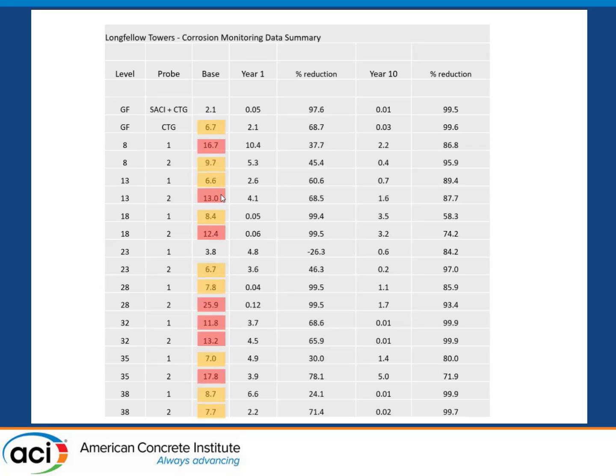And then we have areas that are moderate, in that 5 to 10. Basically, in the baseline readings, at least 7 of those are high, 9 of them are moderate, and only 2 of them are in a low state. After 1 year, we've now only got 1 location that's still a little bit high, and we have 2 that are in the moderate range, but all the other areas look good.